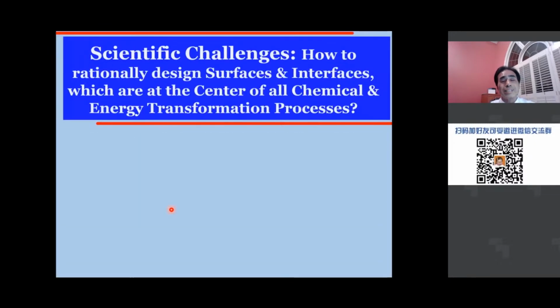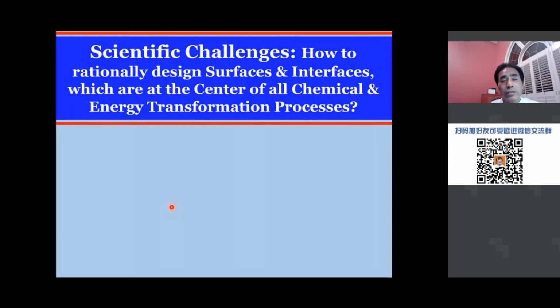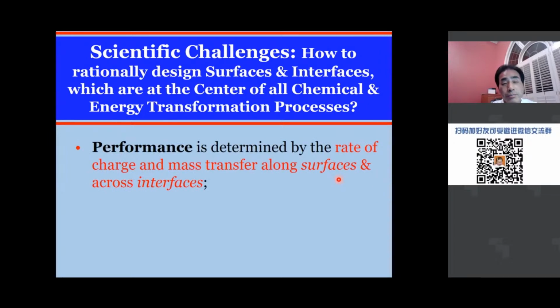So from a scientific point of view, here is our challenge. The question is, how can we rationally design the surface and the interface of this kind of systems? Because we know surface and the interface is right at the center of all chemical and energy transformation processes. And so the performance of all these devices is actually determined by the rate of charge and mass transport along surfaces, across interfaces, and through porous systems. And so that's why the interface is extremely important.